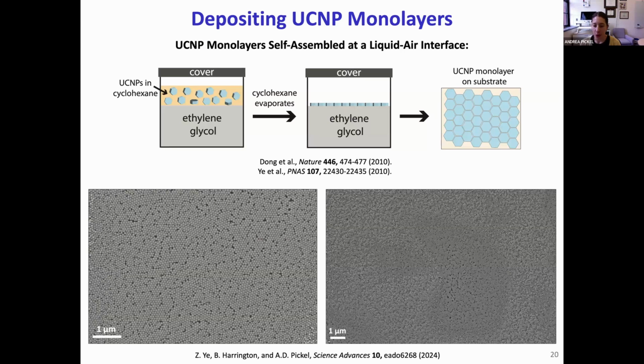So far, all the results I've shown are for isolated single UCNPs, but to do temperature mapping, we need to continuously coat the sample surface with a layer of UCNPs. So to form UCNP monolayers or multilayers, we use an interfacial self-assembly method. We first drop cast UCNPs dispersed in cyclohexane on the surface of ethylene glycol, and then cover the container to slow down the cyclohexane evaporation. And this results in the formation of UCNP monolayers that can then be removed from the solution.